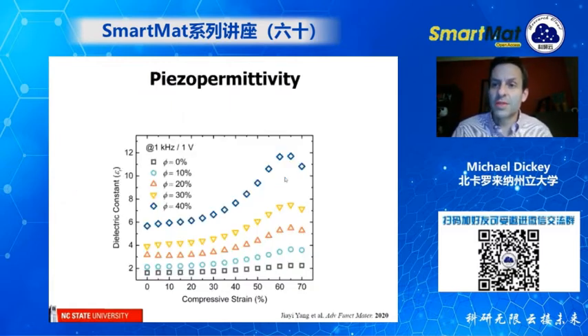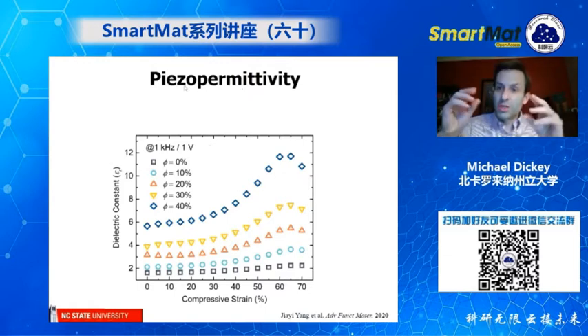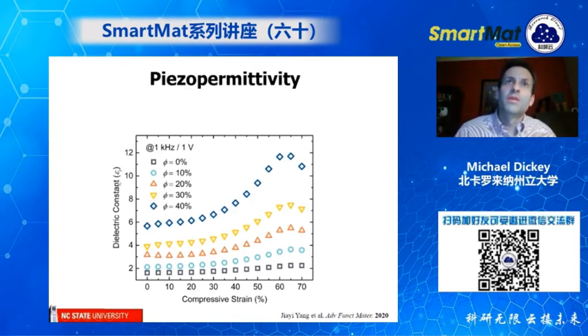Now, one of the interesting things that came out of this is what we call piezo permittivity. Piezo means touch, just touching something, and permittivity refers to the dielectric constant. So this is a plot of the dielectric constant of this foam material as a function of compressive strain. And again, you can see down here, if the silicone doesn't have any liquid metal, it's a very low dielectric constant. It's very low, almost like air. But if you add liquid metal, you can make it larger.